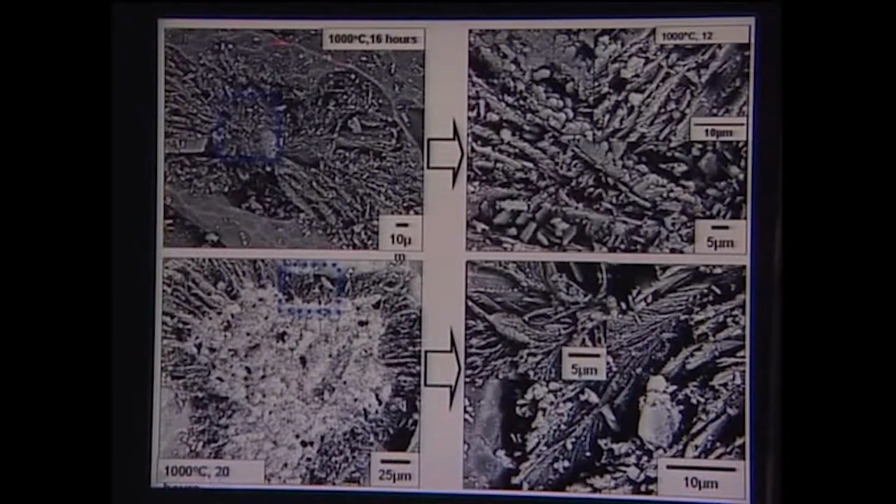Now, this is the crystal domain, let us say, and in this crystal domain, if you focus, this is a kind of nucleus, and from this nucleus these butterfly crystals are growing in different directions. You can see a very characteristic crystal morphology here, more like a fir tree, or a tree leaf kind of pattern. Now, you can consider this as a main leaf, and these are different branches which are formed during this crystallization process.